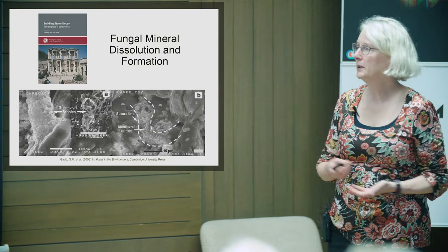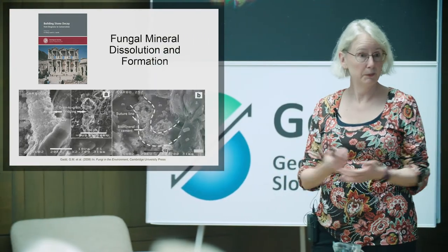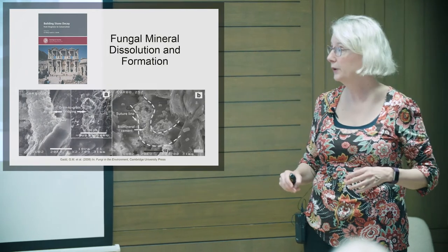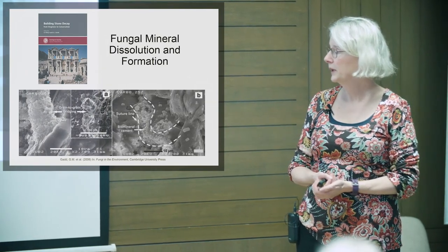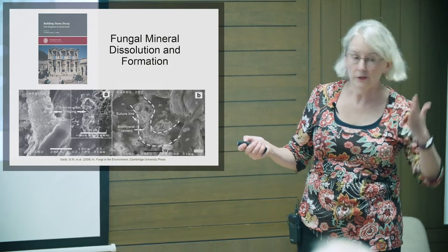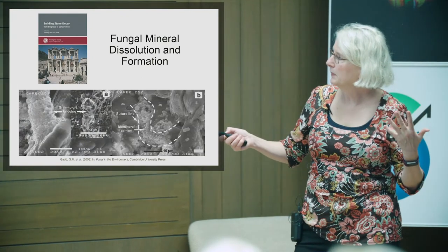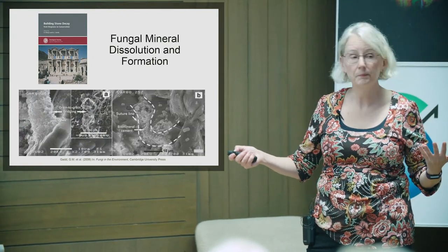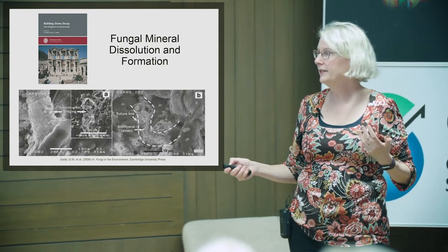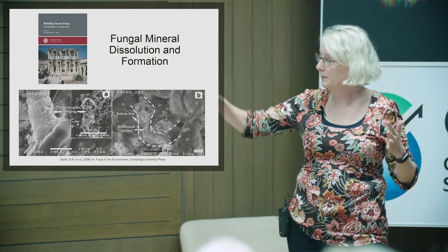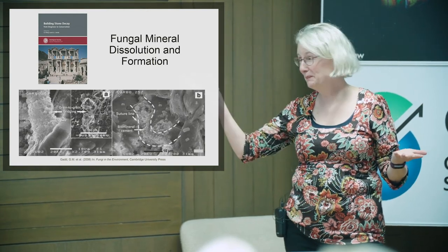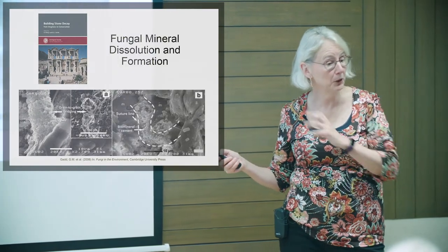So Jeff's also been involved in lots of work about fungi and building stone preservation, which in all of Europe, I'm sure you know, is very important. We don't want our buildings to degrade like this. And a lot of the degradation is partly caused by acid rain, of course, but a lot of it's caused by the activities of microorganisms. So again, we know that fungi can attach themselves to minerals by grain-to-grain bridging. They use their hyphae to extend into the minerals. And then they will react with the minerals and secrete a secondary product, like this biomineral cement. Now, in some cases, that might be a good thing, because maybe the cement is very stable and it preserves the building. But in other cases, the cement is maybe very soluble. So once that cement is formed and it rains, maybe that then starts to dissolve the building away. So it's working with these fungi people and also, again, understanding the minerals and the geochemical processes going on.